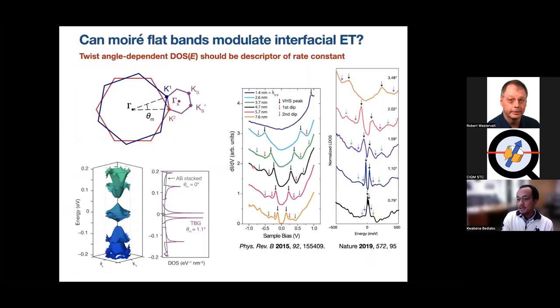Okay. Now, in my group, we looked at these Moiré superlattices, and we started being inspired by the STM work that had been performed to look at the density of states profile of some of these systems. We started wondering whether these flat bands could actually be used as a handle to modulate interfacial charge transfer, because I told you how when you have defects on the surface of materials, that creates localized states that can enhance and facilitate charge transfer.